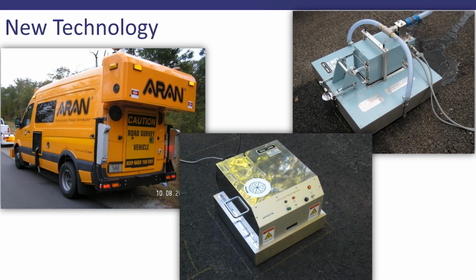So the motor gets it going. There's a hose to spray some water on the pavement, so it's like a wet skid test, and then it drops that fixture, and the rubber skids, they actually screech, so it will scare people out in the field when you're running this. But it will run, it will drop, and it will give you a skid number based on that wet test. But it's a portable type of test. It's kind of cool. Gives you a good relative measure as well.